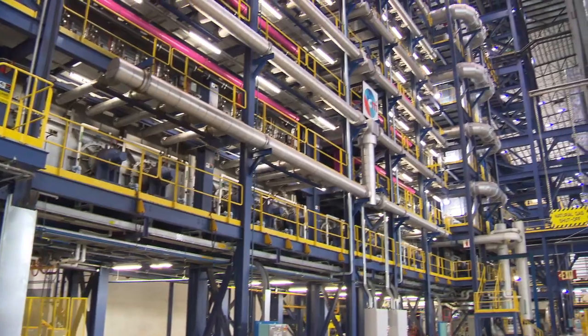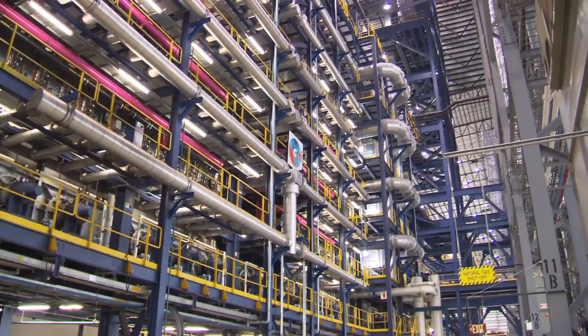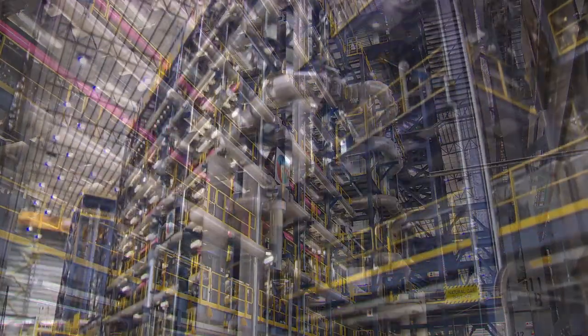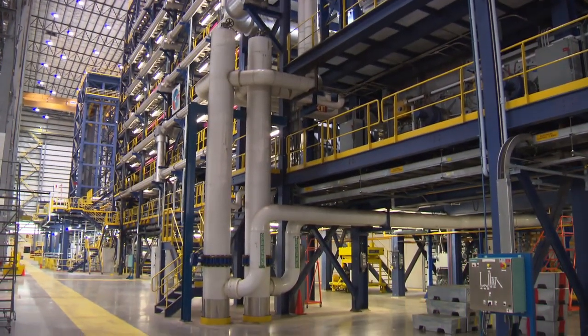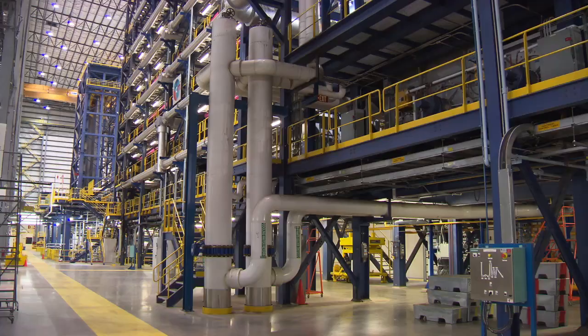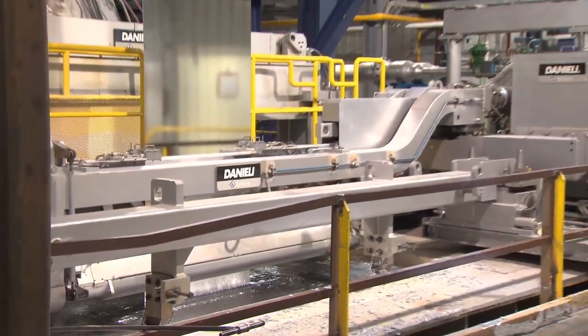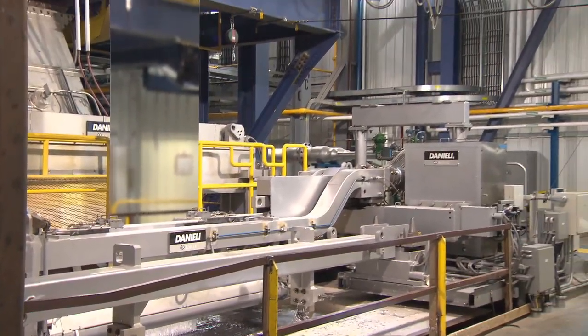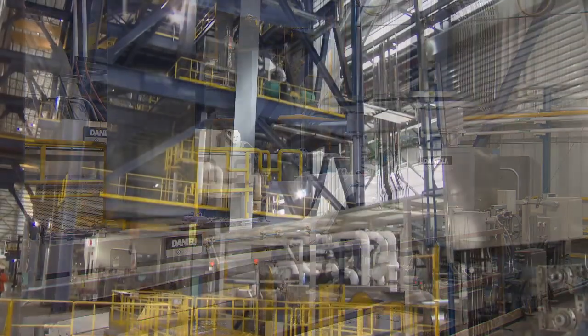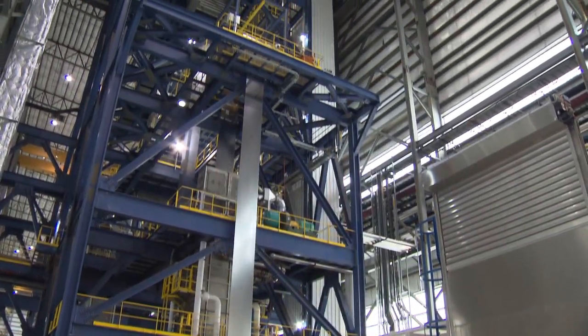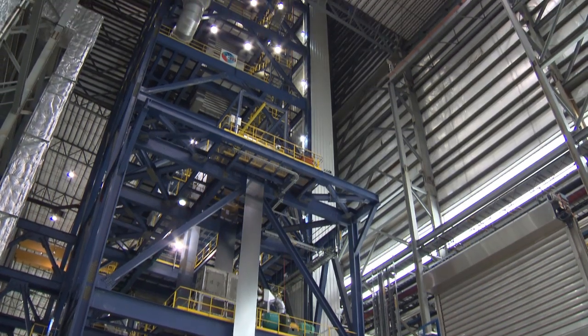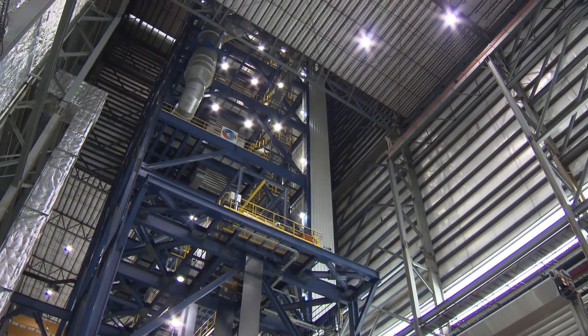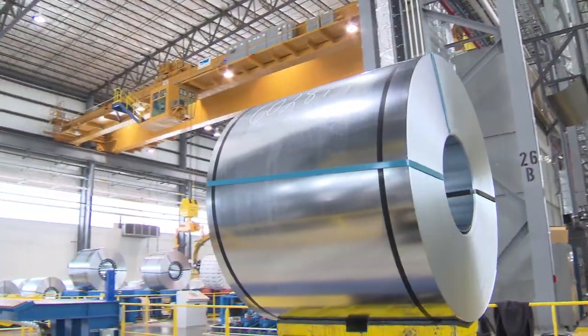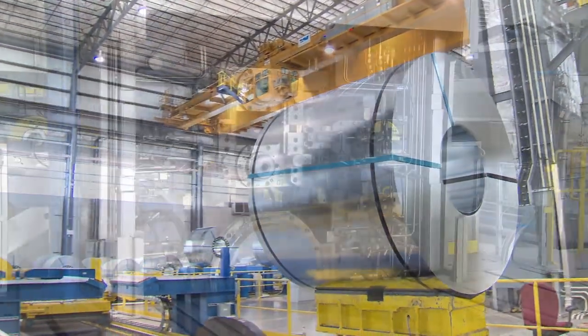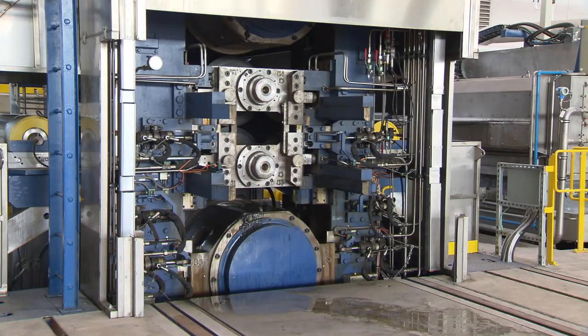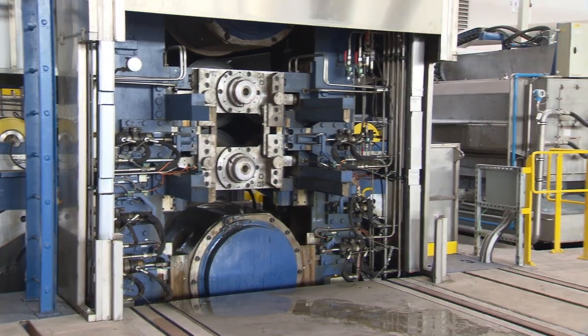A 5-section all-radiant tube computer-controlled furnace heats and then rapidly cools strip temperature for increased steel strength across a wider thickness range. Both galvanized and galvanneal can be produced on the same line using a dual-pot system. The after-pot cooling tower, or APC, is the tallest in North America, providing the longer cool times necessary for advanced high-strength steel production. The skin pass mill applies a uniform texture and protects from strain lines.